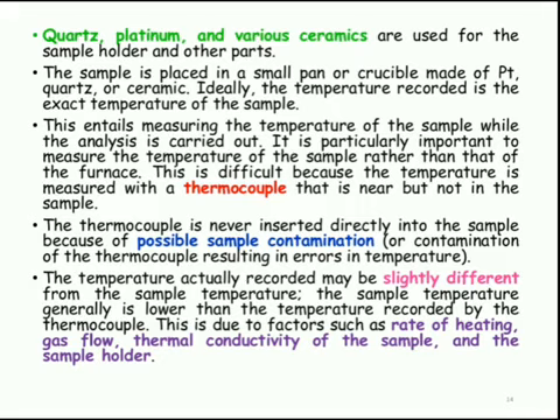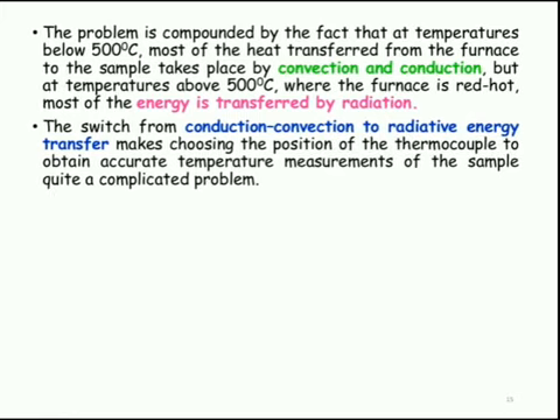And here we saw that the temperature actually recorded may be slightly different from the sample temperature. That is due to the rate of heating, gas flow, or thermal conductivity of the sample or sample holder. This problem is compounded by the fact that at temperatures below 500 degrees Celsius, most of the heat transferred from the furnace to the sample takes place by convection and conduction.